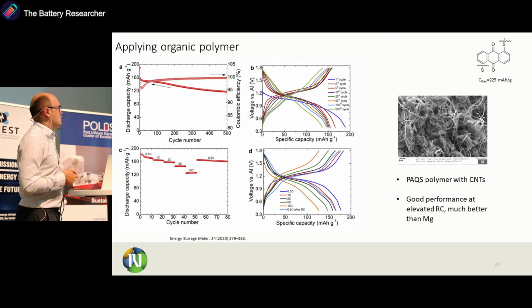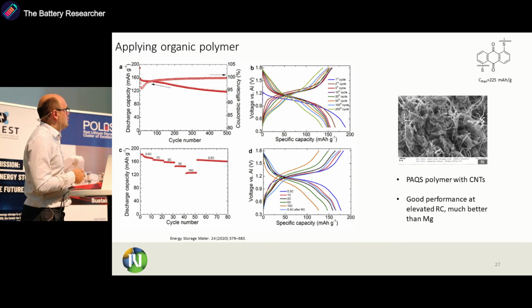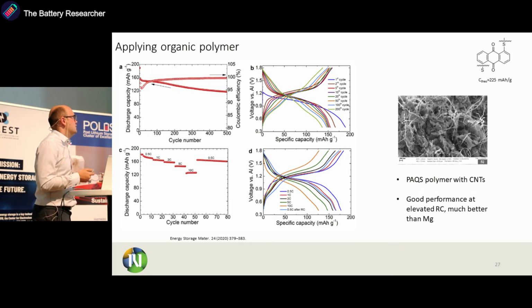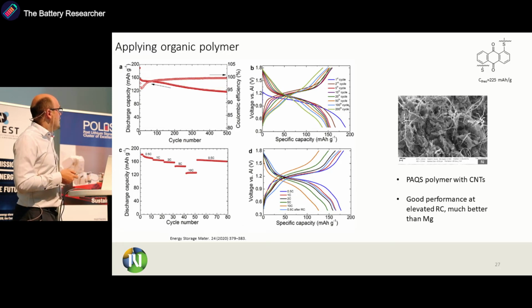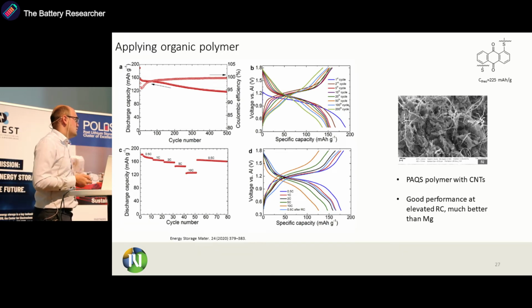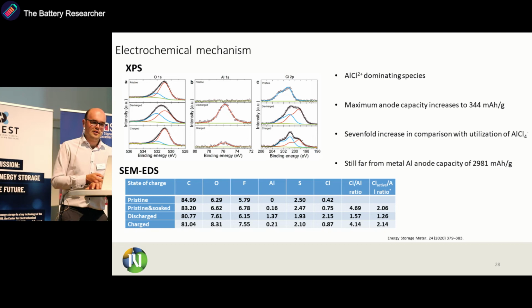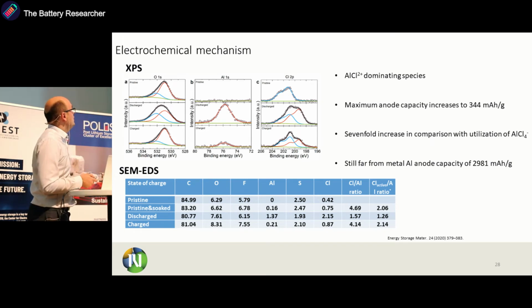Only what was a bit troubling is the fact that basically we have a degradation of electrochemical plateau, because we can see that this plateau is getting less evident from cycle to cycle. The rate capability was also quite good. At 10C, we're still obtaining more than 120 milliamps per gram. And it was also interesting for us that actually it was better performance than in magnesium system. Then we moved on to the mechanism investigation.